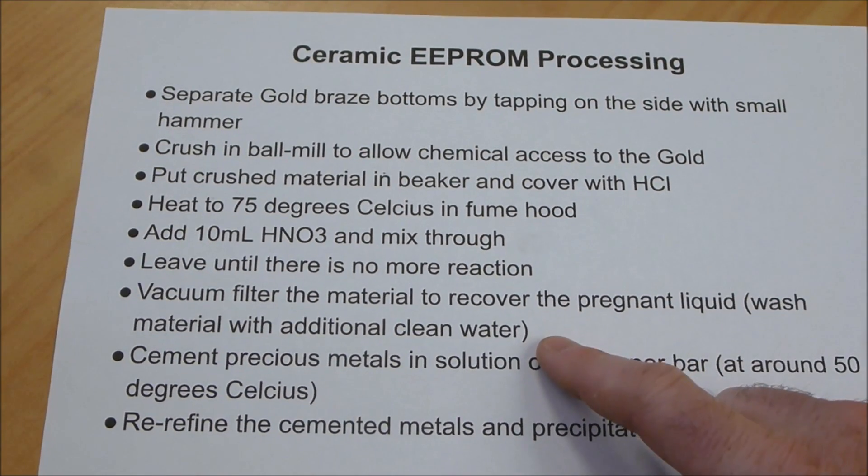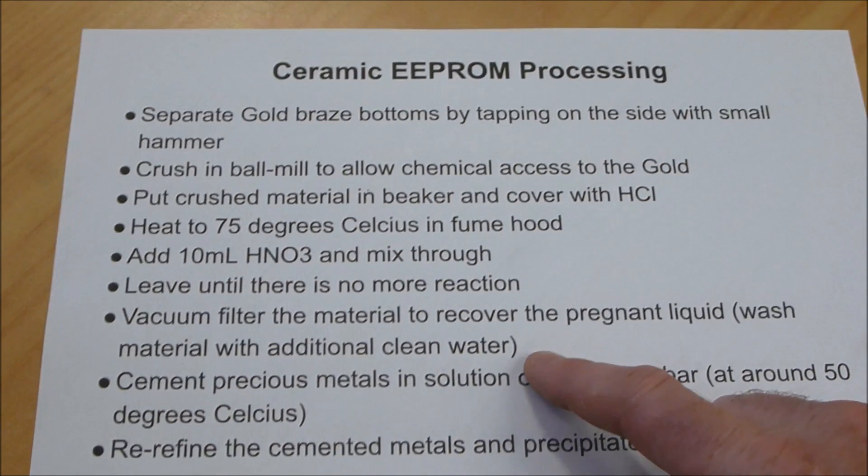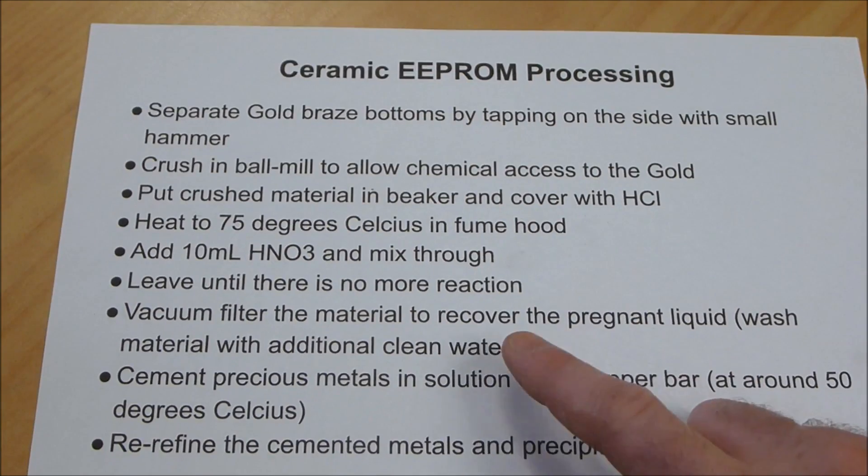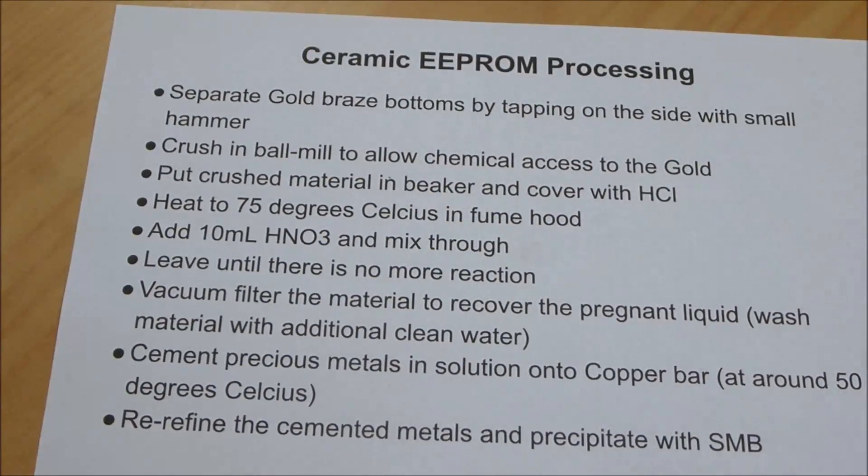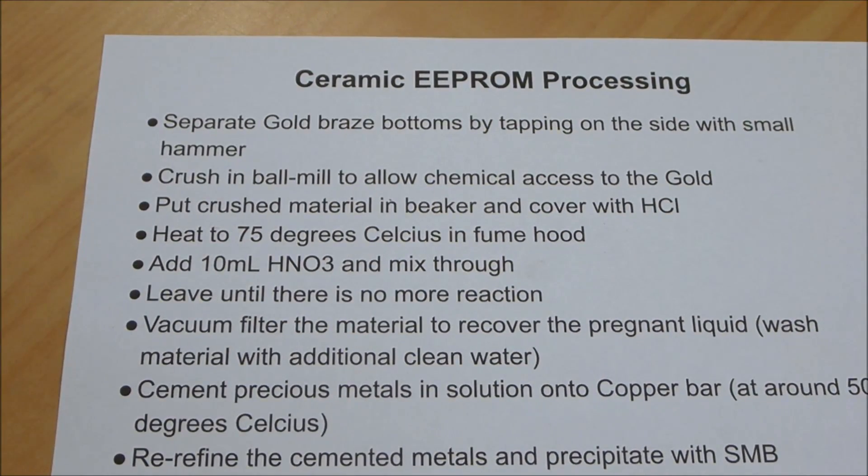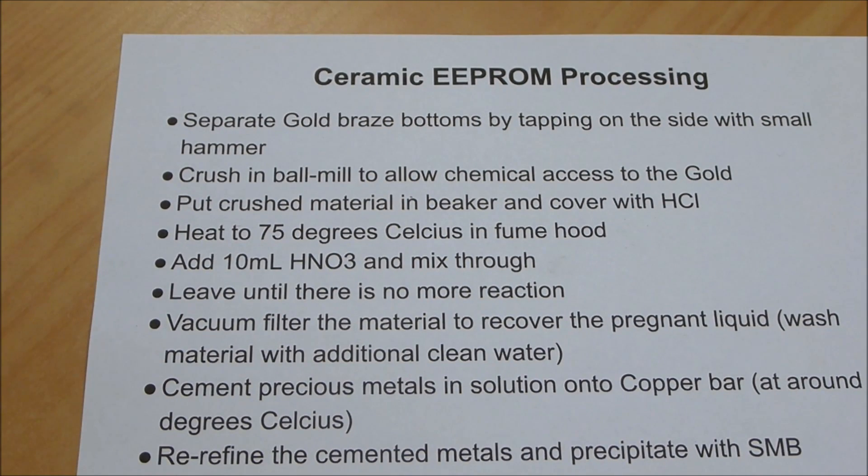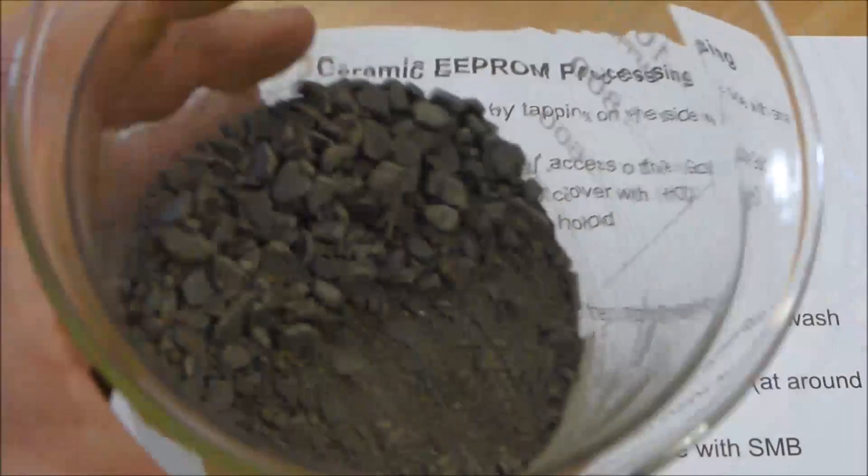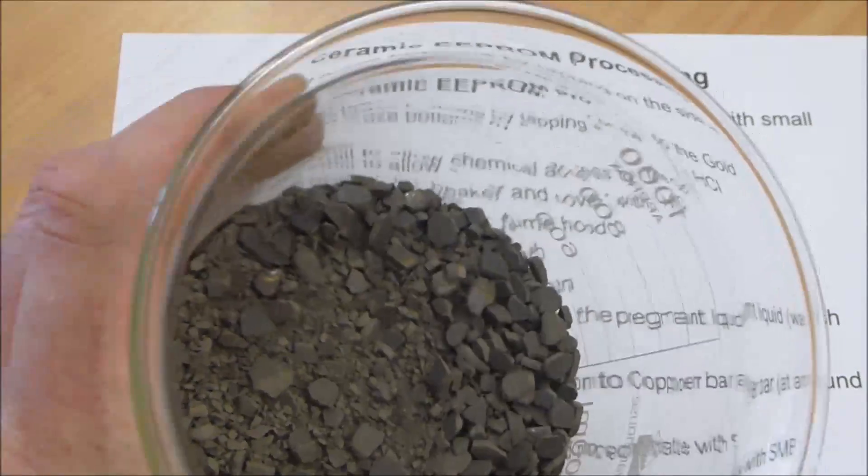Then I'm going to vacuum filter all that material to recover the pregnant liquid, and I'm going to wash the leftover bits of ceramic with additional clean water probably a couple of times to get as much of the pregnant acid out of it as I can. At that point this stuff is actually fairly safe to dispose because it's very inert. If you've washed it relatively well it does absolutely nothing—it's basically bits of sand, it's rock.